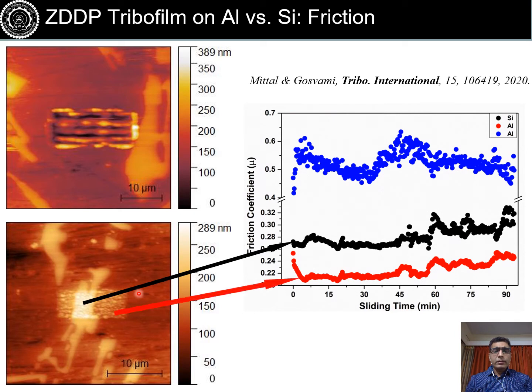We also see that friction coefficient now we can measure because we are using a microspherical probe, ball and disc kind of tribometer type of setup, which we have now started using by attaching a microsphere to the AFM cantilever. So these friction coefficients also correlate very well to this friction and wear observation. So if you see, the coefficient of friction on aluminium is significantly lower when there is no wear of aluminium and there is no damage to the surface.